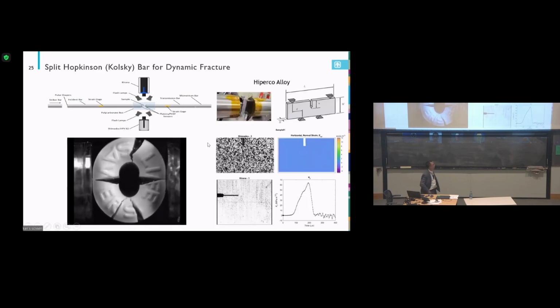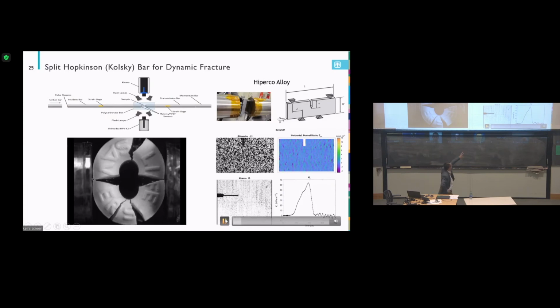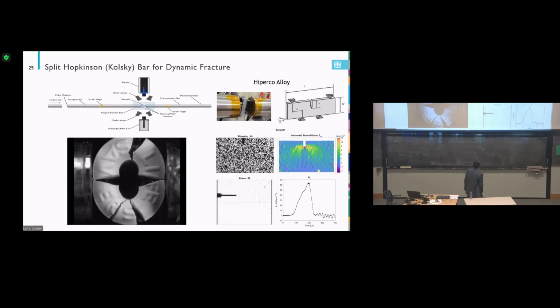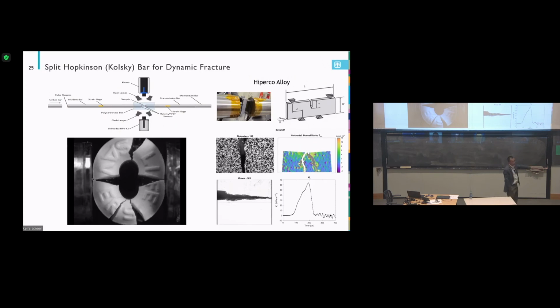Oops, this is a real one. We test the Hiperco for 4-point bending, with different specimen designs. So we try to understand the fracture toughness. This is designed for the mode 1 fracture toughness, dynamic fracture toughness, because Hiperco is a very brittle material. So you can see we have the V-notch, we have the pre-crack over there. Then we just do the 4-point bending to see how the specimen got fractured, how the crack initiated. So this is on both surfaces. You can see the crack tip or the pre-crack over there. You see the crack start from the tip and then propagate. Both sides. And from this, we can calculate the K1C fracture toughness, dynamic fracture toughness, mode 1 toughness. So that's how we do the fracture toughness.